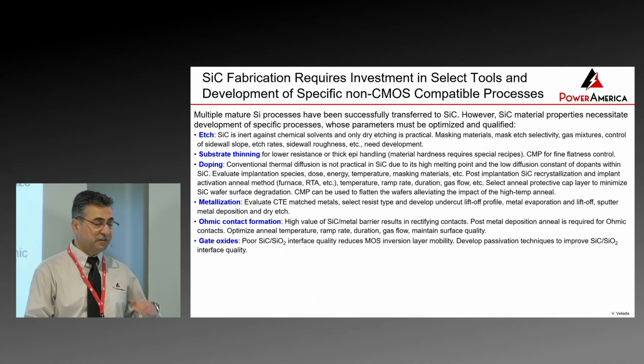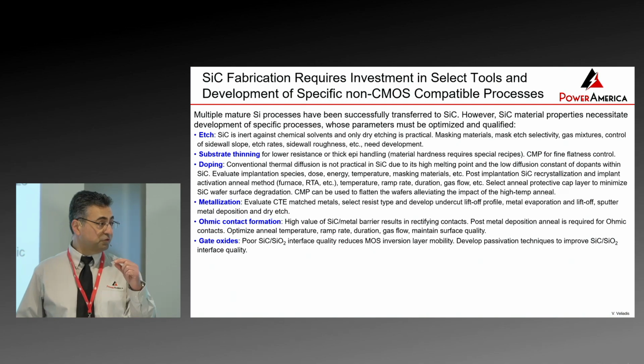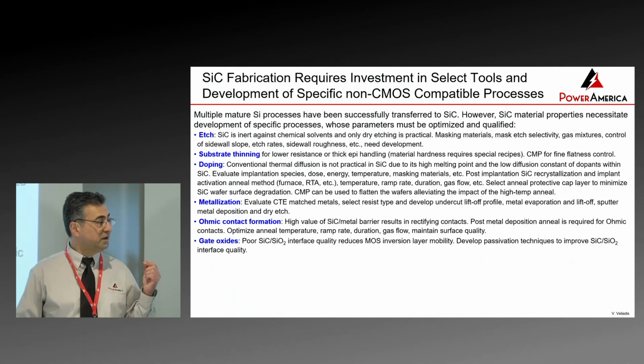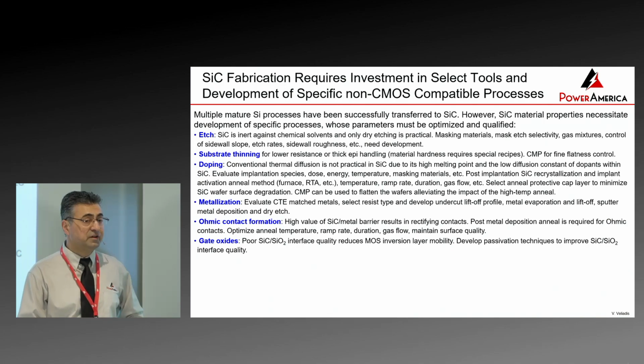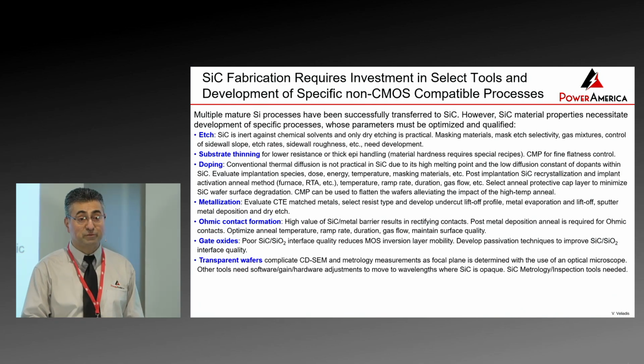The gate oxides: the silicon carbide oxide interface has a lot of traps, and that can lead to a lot of threshold voltage instability, and we'll hear about that tomorrow from my friend Aivars Lelis. That's something where a lot of work has gone in, and there's a lot of room for improvement here, a lot of room for improvement.